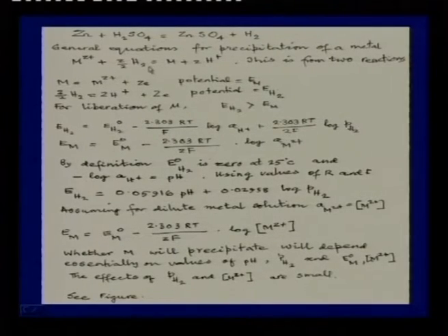But we can make this thermodynamically feasible by increasing the pressure of hydrogen and reducing the hydrogen ion concentration, and try to push it to the right. This will never be possible for sodium or potassium or cesium, which are so reactive. It does not matter how much hydrogen pressure you apply or how much you lower the hydrogen ion concentration, which means how much acid you make, this will not take place.